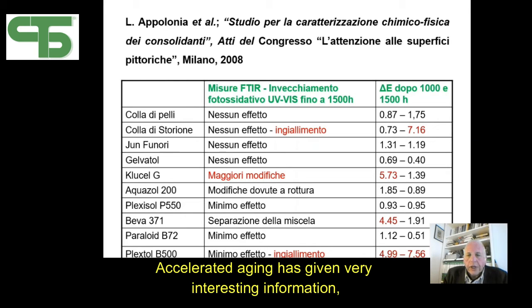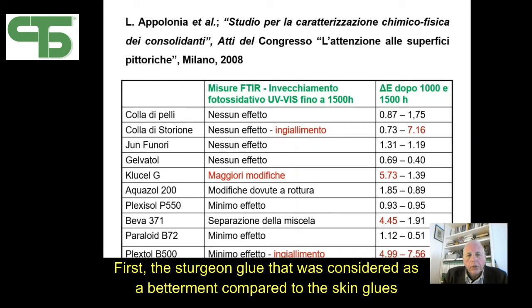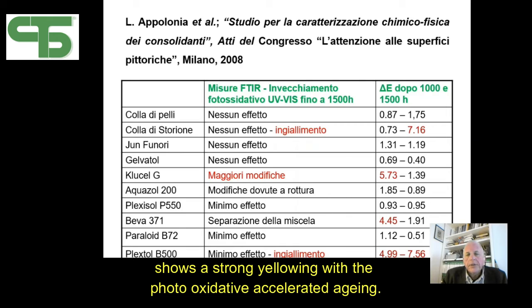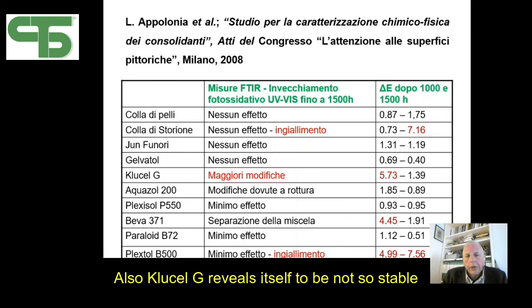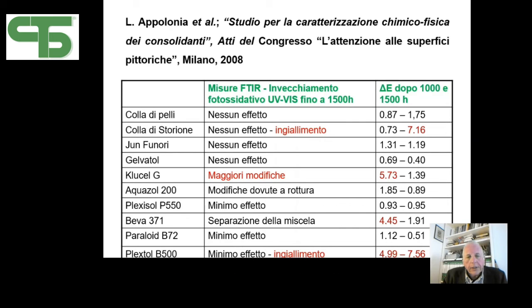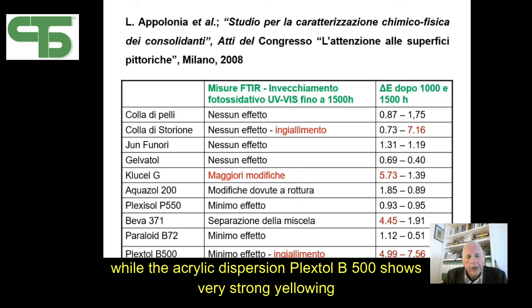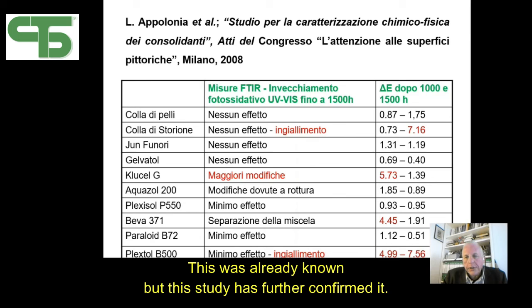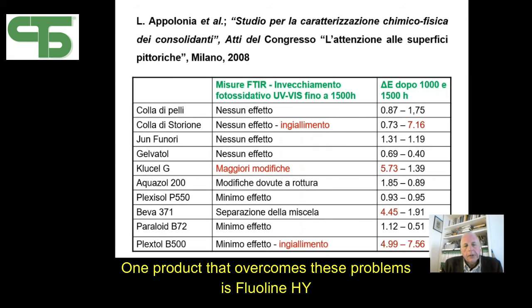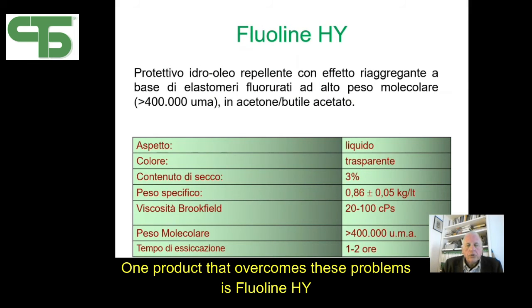Accelerated aging has given very interesting information. First, the sturgeon glue that was considered a betterment compared to the skin glues shows a strong yellowing with the photooxidative accelerated aging. Also, Klucel G reveals itself to be not so stable, while the acrylic dispersion Plextol B500 shows very strong yellowing, but this was already known, and this study has further confirmed it. One product that overcomes these problems is Fluoline HY.